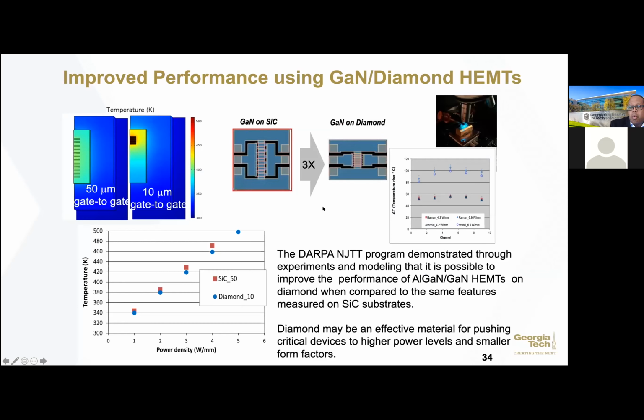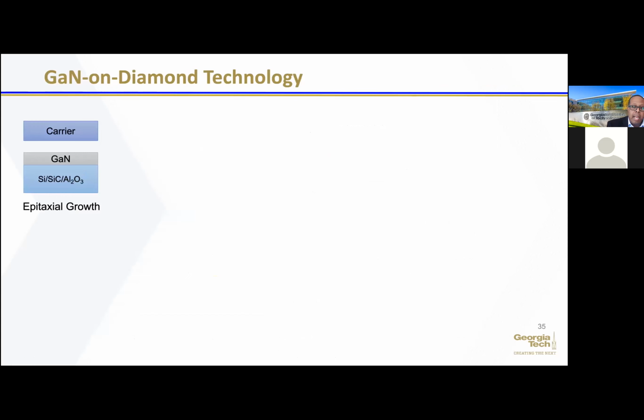We were able, working with Raytheon and others on our DARPA NJTT program, to demonstrate that you could take this GaN on silicon carbide device, shrink it down by a factor of 3, and this device is not hotter than this one. And so there's a very interesting effect of going to diamond in order to help dissipate this thermal energy. So how is this done?